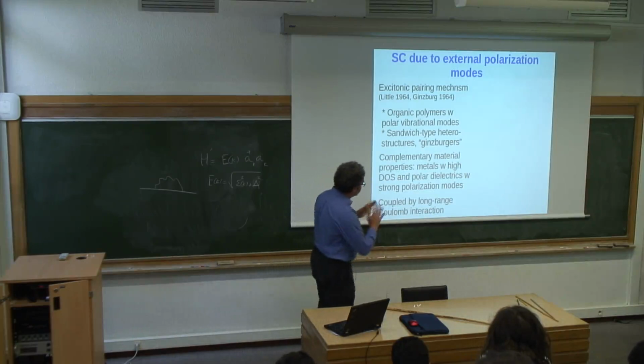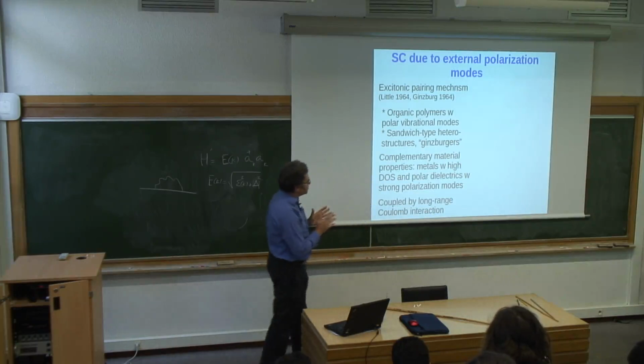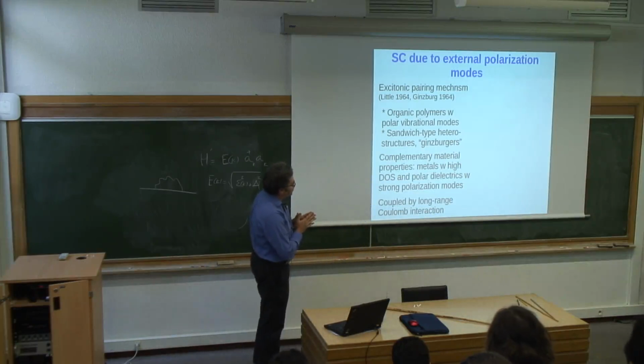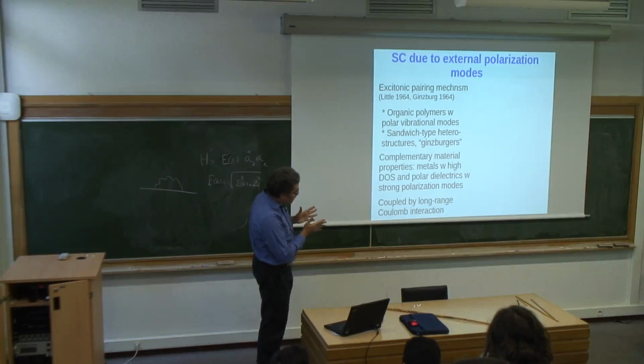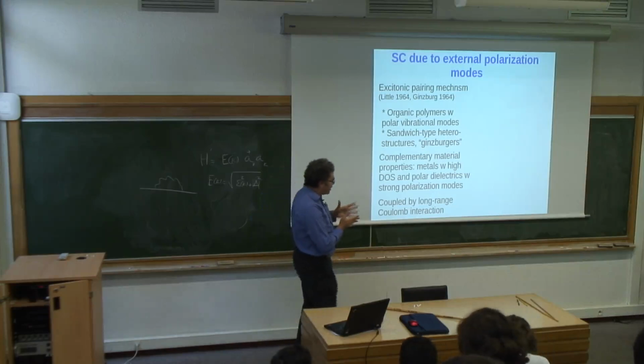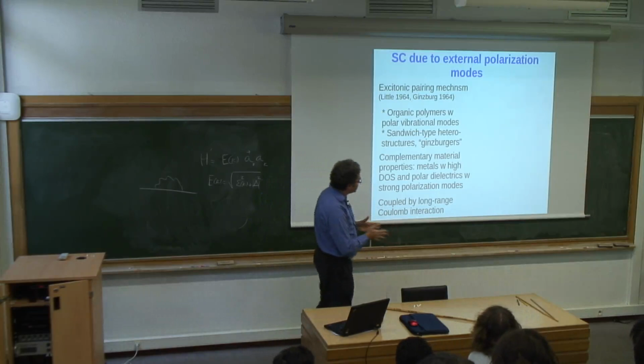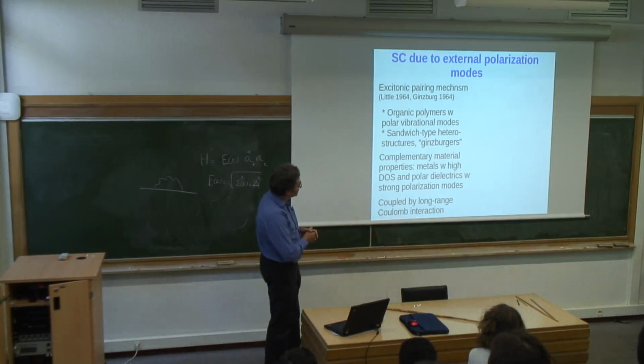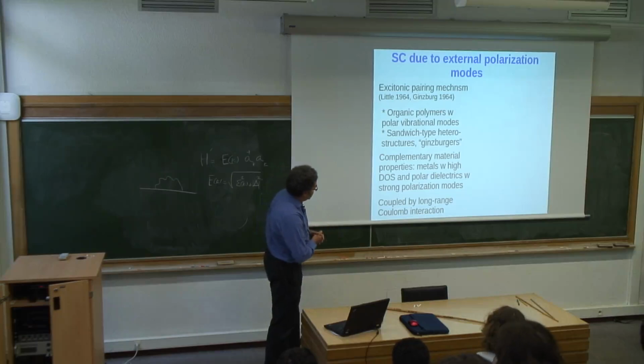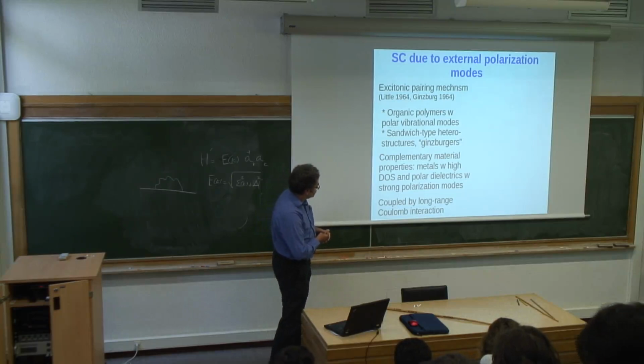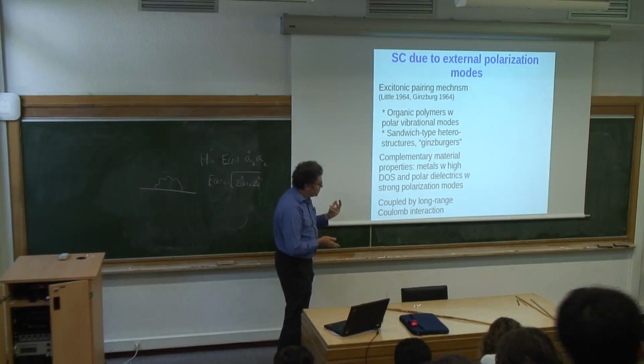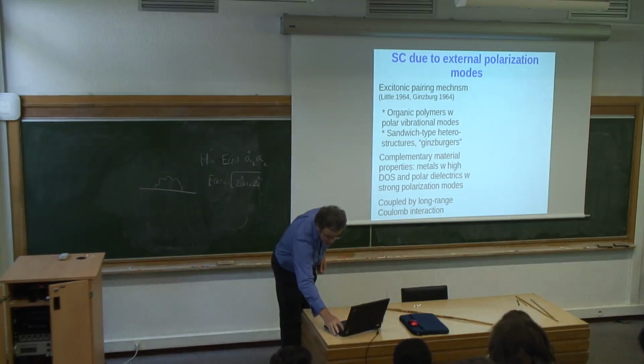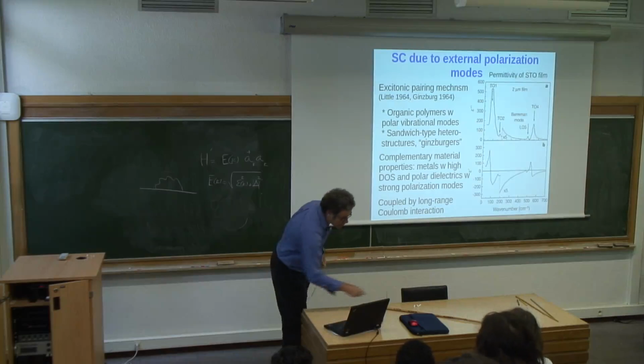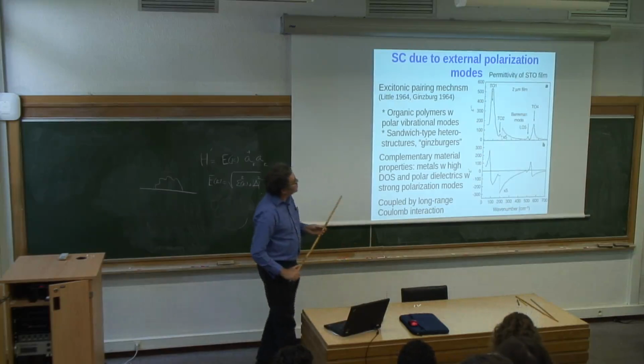Like I said, using complementary materials is very attractive from a theoretical point of view, because you can have a material with high density of states, but perhaps not very strong intrinsic electron-phonon interaction. And then if you combine it with a polar dielectric placed around it, you might have a very strong dispersive part of Coulomb interaction. And indeed, you can have attraction.